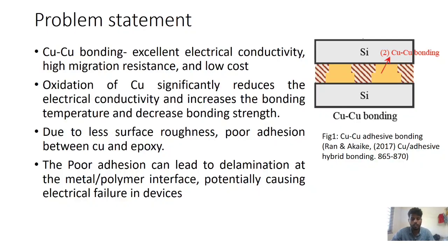So, to meet the need of high temperature electronic applications, nanoparticle sintering comes into the picture. Copper bonding has excellent electrical conductivity, high migration resistance, high thermal conductivity, and low cost. But copper nanoparticles are prone to oxidize, which reduces the bond strength, reduces the electrical conductivity, and increases the bonding temperature. Similarly, we find some issues in the copper epoxy bond also due to less surface roughness. The adhesion between the copper and epoxy is too poor, and it results in failure in the device.